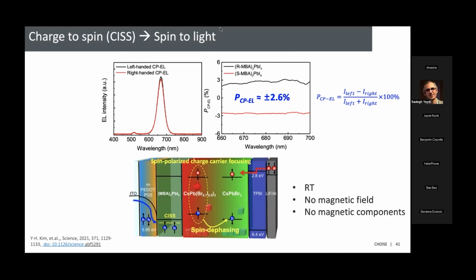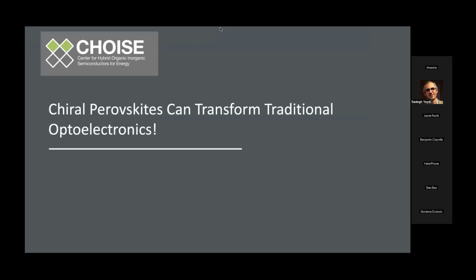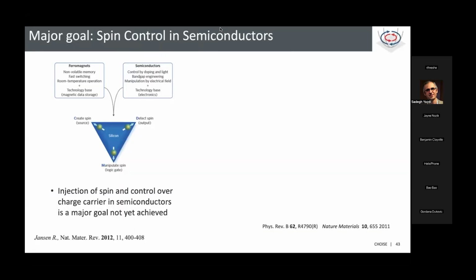We are showing that we can get spin accumulation in this non-chiral emitter layer without any magnetic fields at room temperature and no magnetic components. So that's impressive. So chiral perovskites can also transform traditional optoelectronics. All right, so this is a major goal, actually, this paper from 2012 over here. People know, I showed you the magnetoresistance effect. Those are with ferromagnets and metals, and you can control spin in that kind of system. And we all know semiconductors do all sorts of great things. So of course, people want to marry these two and control spin, charge, and light, right? That's what we want to do.